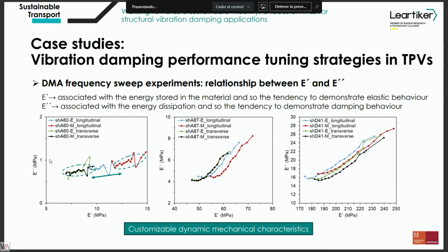So it was also very interesting to find that at low Shore hardnesses, in this Shore A60, we are able to somehow customize the dynamic mechanical properties of these materials. That means that if in the final performances we would like to have different ratios between the static and dynamic stiffnesses, different loss factor or dampening capabilities, we should be able, if we are able to control the process and the final microstructure that we have in these materials, to optimize and also customize the final properties that we will obtain at material and product levels.